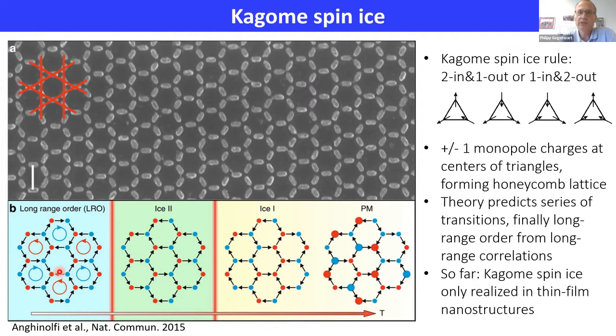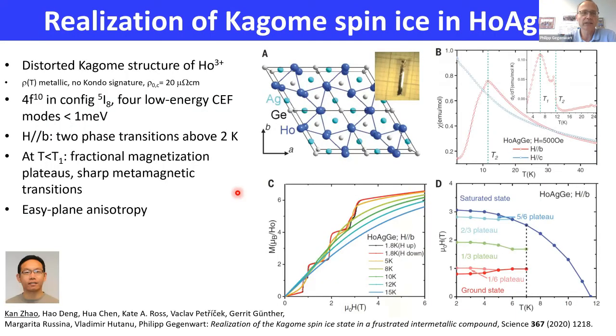Now, up to now, experiments on Kagome spin ice were limited to magnetic nanostructures, which are based on ferromagnetic thin films of nanometer-sized regions, where shape anisotropy dictates that the total magnetization has to point inwards or outwards of the triangular units. And of course, it would be nice to have a real crystalline material which features the Kagome spin ice physics. And this was really the major discovery by Kan Zhao, who found that this physics is realized in holmium silver germanium.